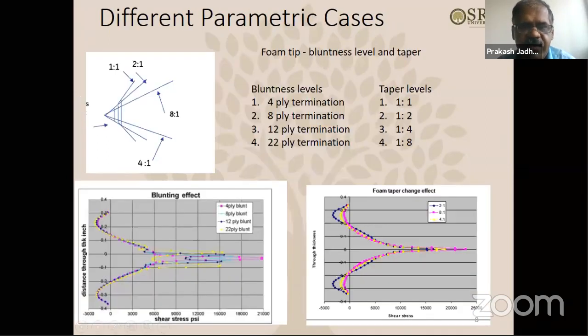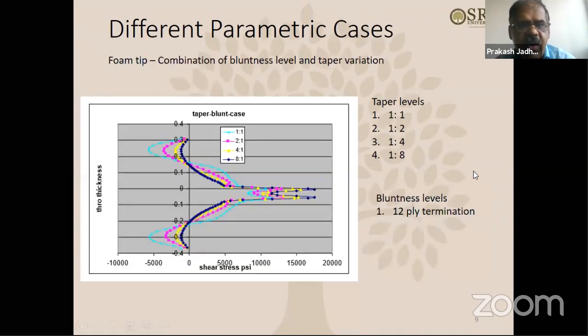So again, a combination of the blunting level and the taper variation. That also we tried, in the sense that if you take one case of the ply termination, that is 12 plies ending at the end, and then you try to vary the taper level like this. You fix one parameter and you vary the other parameter. So the first parameter was ply termination, that we fixed, and the other parameter, taper variation, we varied. So that also gave different results. At the tip, you can see the maximum interlaminar stress level is varying.